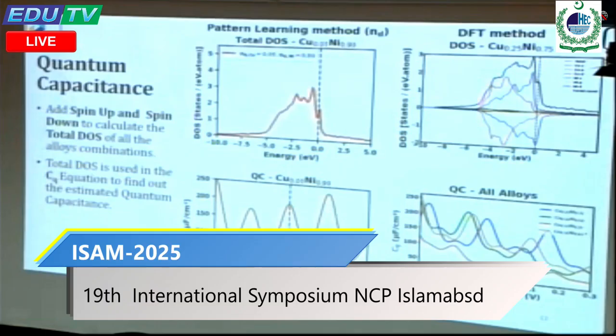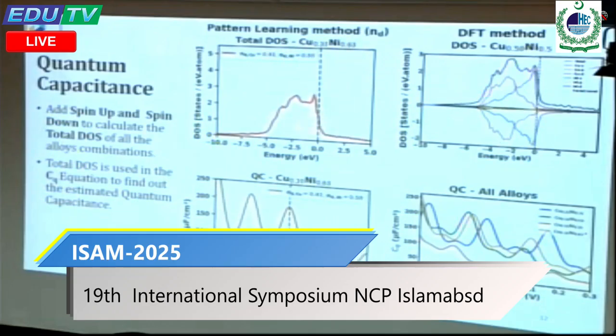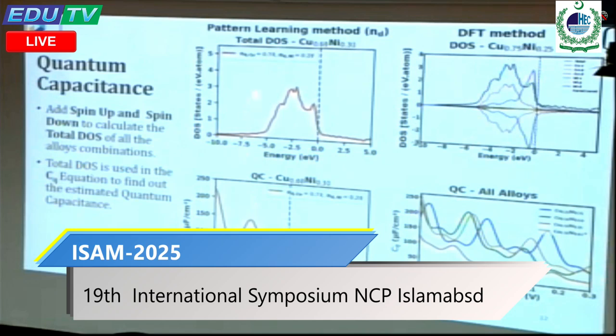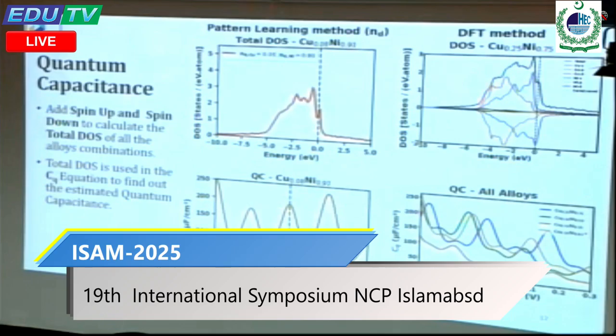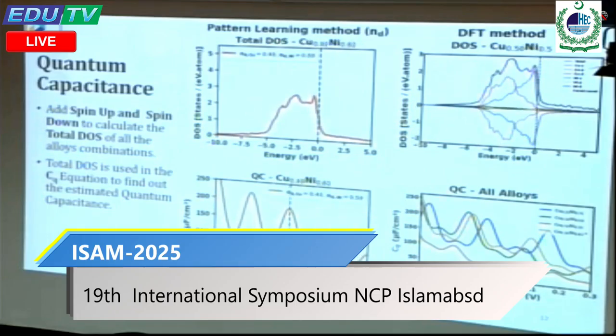And here is a video demonstration of how the composition is actually affecting the density of states at the Fermi level and eventually the quantum capacitance. These are the actual DFT results, and these are the predicted ones with accuracy of about 94% if we calculate both up and down. So we add spin up and spin down density of states to calculate the total density of states, and then for each composition we can calculate a different quantum capacitance.